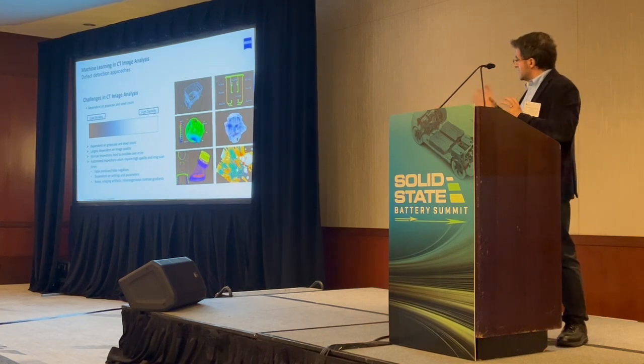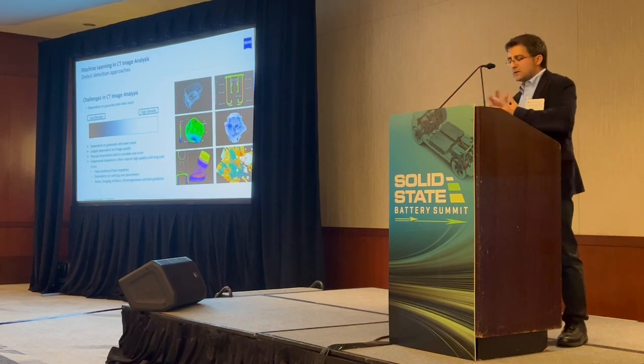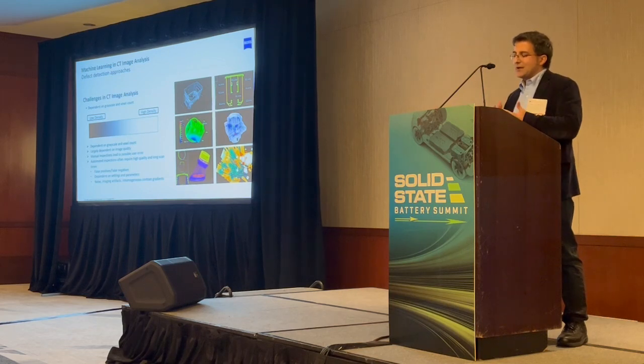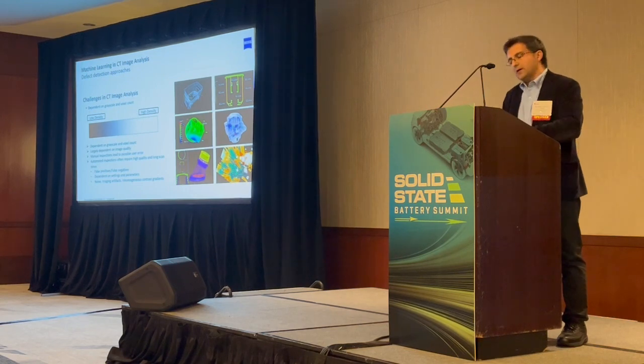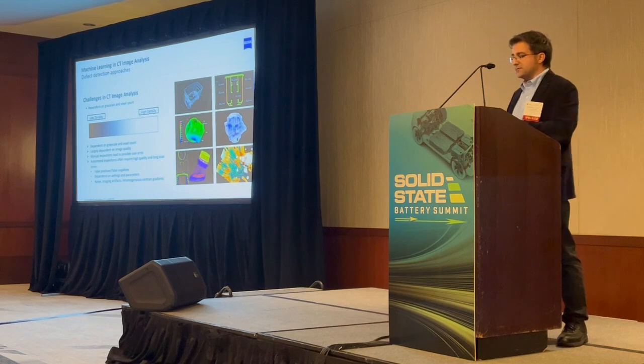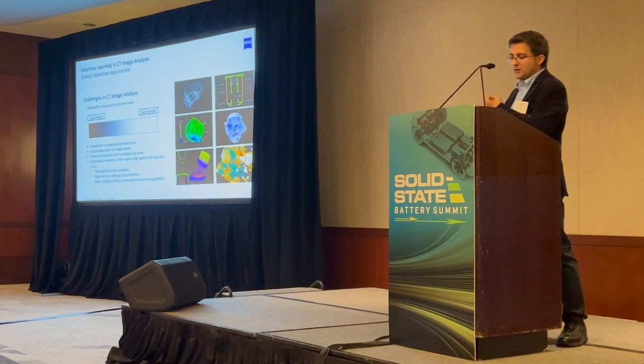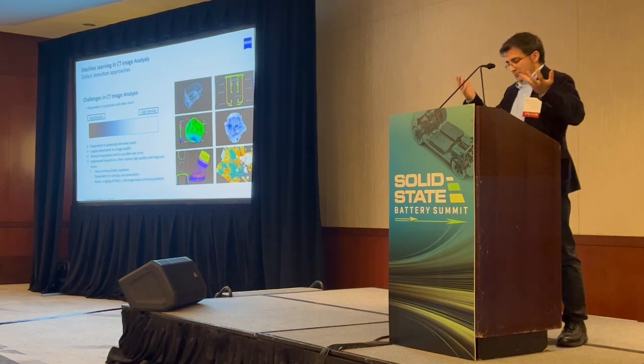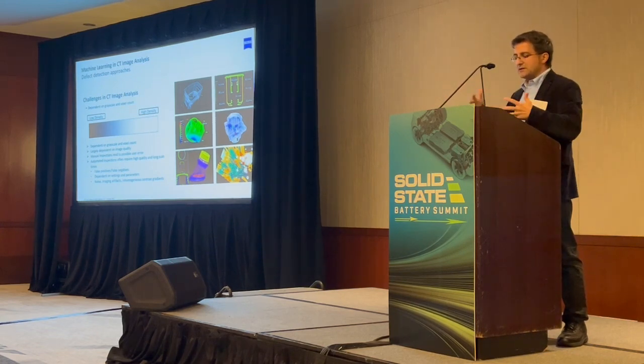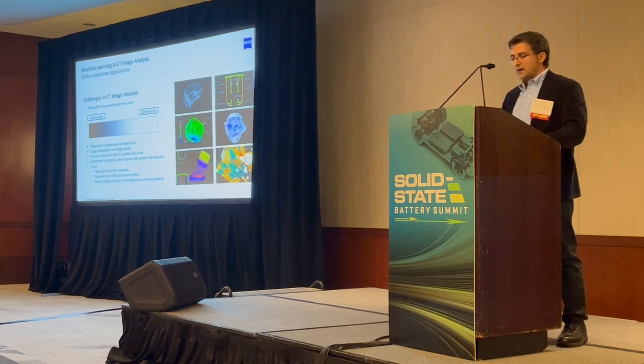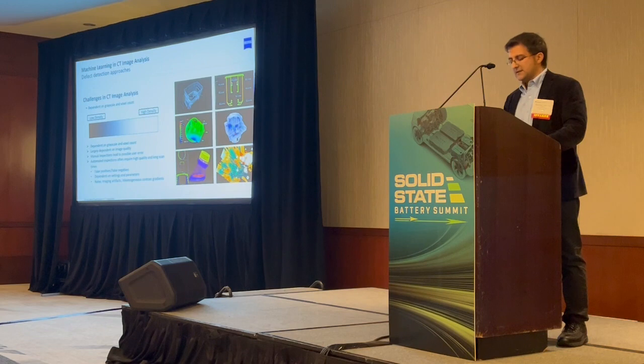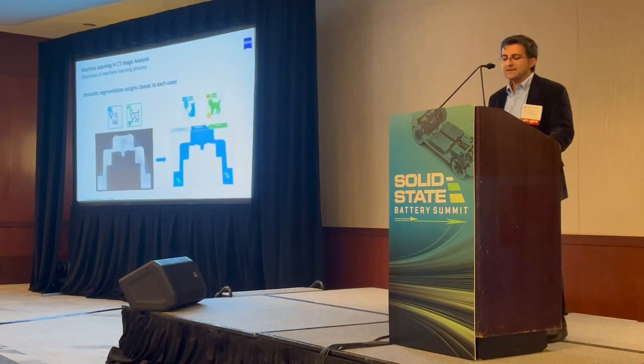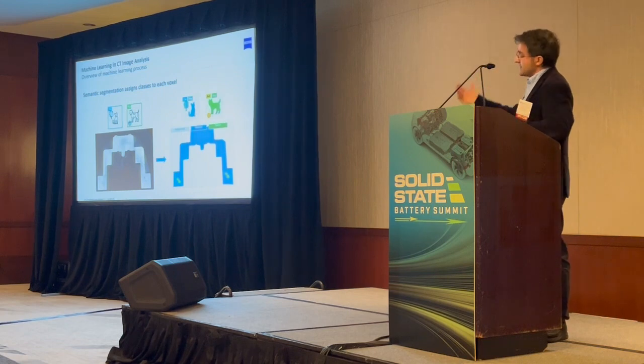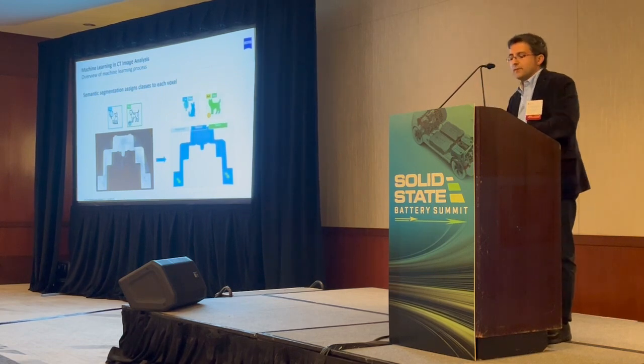And generally, the traditional methods use thresholding algorithms, but then there is the problem of how good those segmentation approaches could be, and what's the criteria that you use. The problem is even more challenging because there are effects on those algorithms by noise, by image artifacts that are usually in X-ray CT, and the inhomogeneous contrast gradients that are the natural data that you obtain from a CT scan. So one alternative to the traditional segmentation algorithms is to use machine learning again.